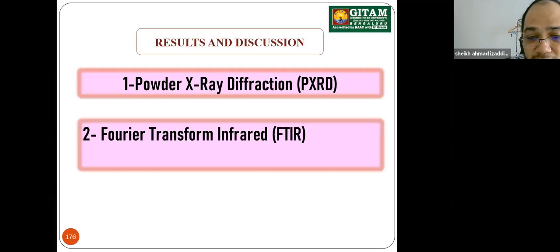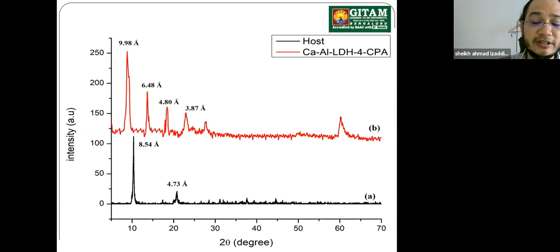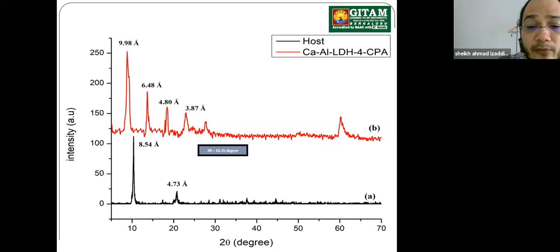So for results and also discussion. The PXRD figure demonstrates the PXRD patterns of calcium aluminum LDH host and also calcium aluminum LDH 4-CPA nanocomposite. From the diffractogram, which is the black color, the calcium aluminum host shows a sharp, highly crystalline and intense peak that can be observed at 2 theta 10.35 degrees. The basal spacing is calculated using Bragg's law formula, and the result obtained was 8.54 Angstrom. This basal spacing indicates that the interlayer gallery of the calcium aluminum LDH accommodates counter anions, which are water molecules and also nitrate.